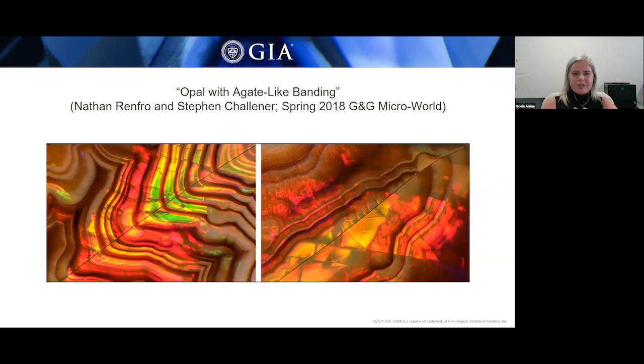Microscopic examination revealed a couple of cracks in this stone, and these cracks are actually healed naturally with opal filling. Observing that assisted with understanding the order of events that occurred to produce the pseudomorph specimen. It's thought that the deposition of the chalcedony occurred in order to produce that wavy banded structure, which was followed by stress fractures that laterally shifted the stone, creating these micro faults that you can see in these two photos. These faults were then healed with a secondary deposit of opal, which also replaced the chalcedony while preserving that original agate structure.